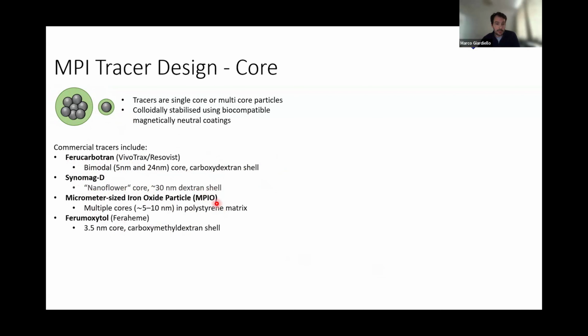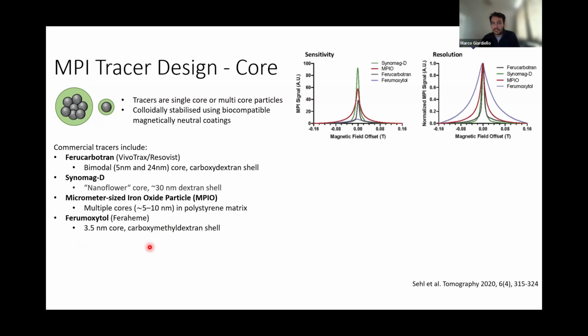You have these larger particles, MPIOs, that are quite often surrounded by polystyrene, so they're very, very stable, and they're much larger, so they have a very strong magnetization. And then you've got the Ferahem at the bottom, which again is a smaller core with a carboxydextran shell. And in this paper here, they compared them. So you can see that very strong signal comes from Synomag-D, followed by MPIO.